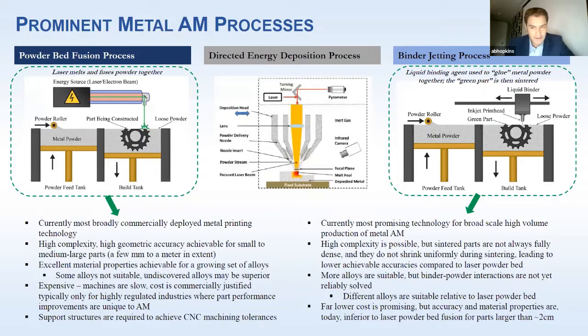invites warp, and it doesn't shrink uniformly necessarily, nor does it, when you shrink, get to full density in the way that you would with powder bed fusion. So instead of 99.9% of theoretical density, you might be at 95 to 98%, or if you have a really nice powder, you can get to 99.5%. Still not quite as good, but that's good enough, by the way, to get properties from the 99.5. So you shrink, you have some warpage, the part bends when you shrink, there are residual stresses, you have these thermoelastic effects, and it's hard to predict that. So your accuracy is not as good as powder bed fusion. If you make a big part, it can break. Those are problems, but at the end of the day, it's much, much less expensive.